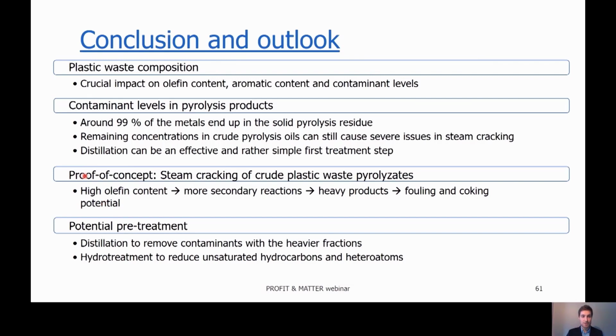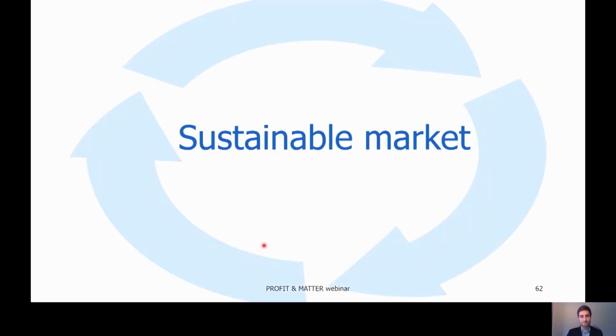This has shown that we really need to pre-treat these feedstocks in order to make them more feasible for steam cracking. Potential pre-treatment was already mentioned with distillation to remove contaminants, but also hydrotreatment is a very potent technique to actually reduce unsaturated hydrocarbons and heteroatoms. Using hydrotreatment, we can most likely produce a very nice feedstock based on plastic waste, comparable to fossil naphtha. Thank you very much.